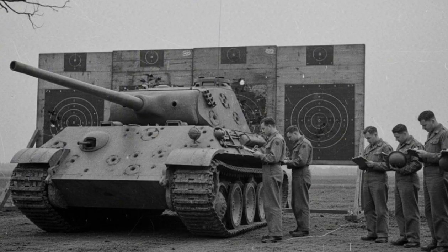At 1,000 yards, the 76mm M62 failed to penetrate the 80mm glacis at 55 degrees, confirming German reports that the Panther's frontal armor resisted all Allied medium tank guns. At 600 yards, the 90mm M82 penetrated cleanly, producing a 100mm diameter hole with minor spalling. The lower glacis, 60mm at 55 degrees, was vulnerable at 900 yards to the same projectile. Side armor, 40mm vertical, was perforated by 57mm M70 AP at 1,200 yards. Observations recorded excellent ballistic shaping and efficient use of slope to reduce effective impact angle.